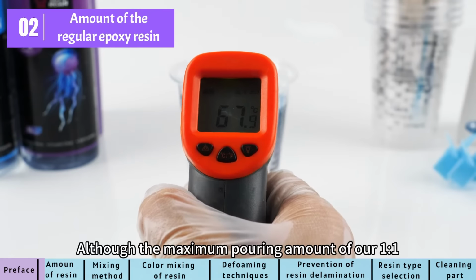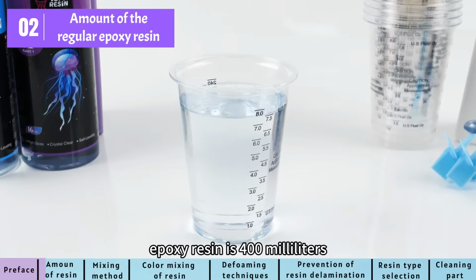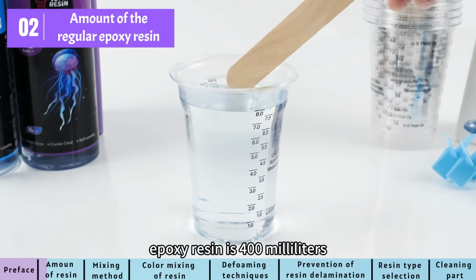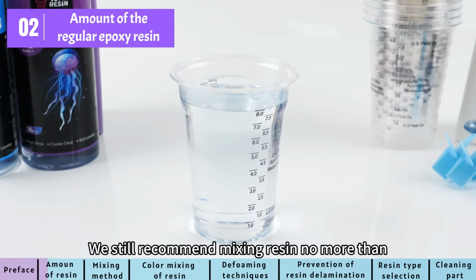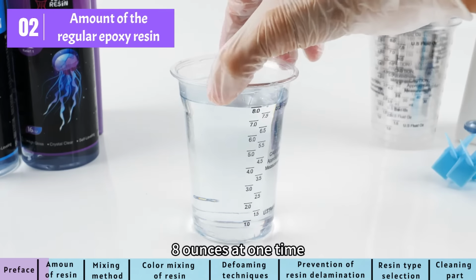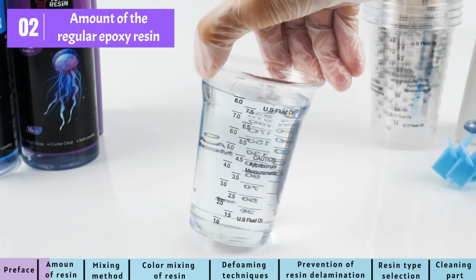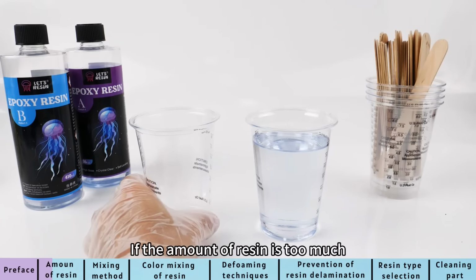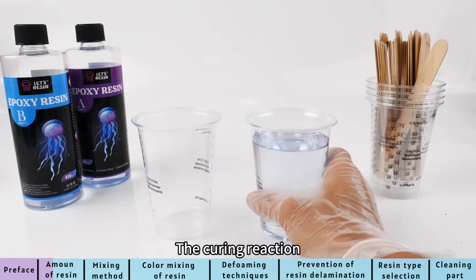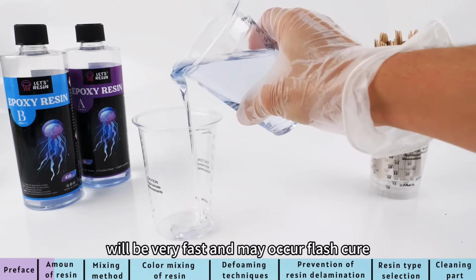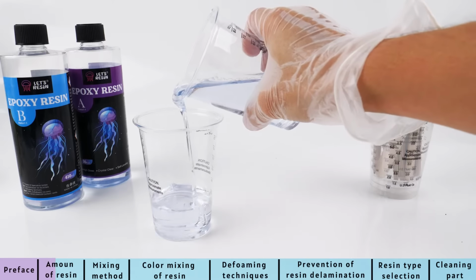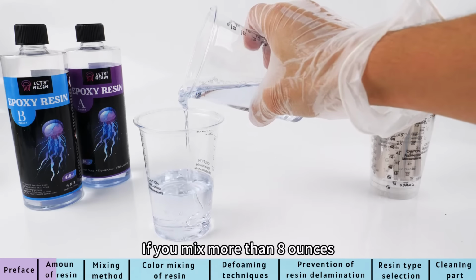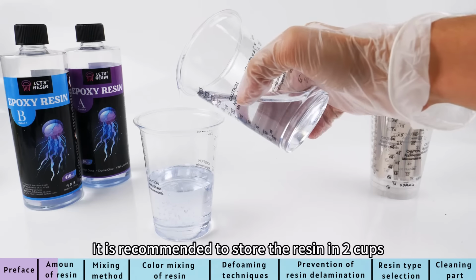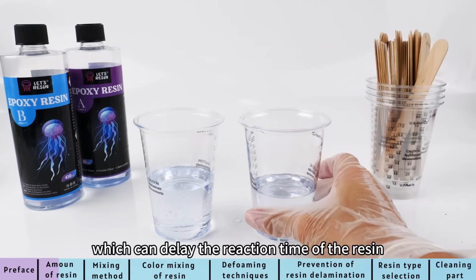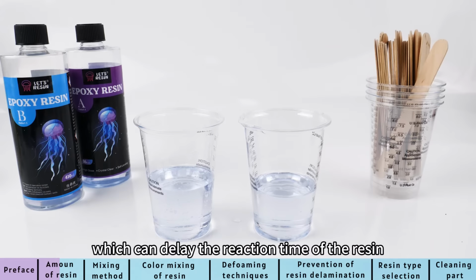Although the maximum pouring amount of our 1:1 epoxy resin is 400 milliliters, we still recommend mixing resin no more than 8 ounces at one time. If the amount of resin is too much, the curing reaction will be very fast and may occur flash cure. If you mix more than 8 ounces, it is recommended to store the resin in 2 cups, which can delay the reaction time of the resin.